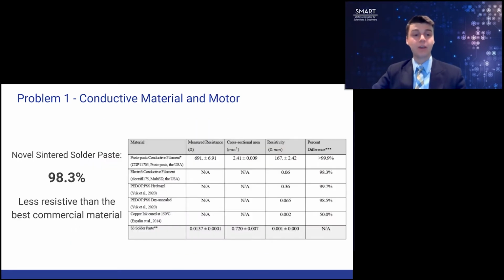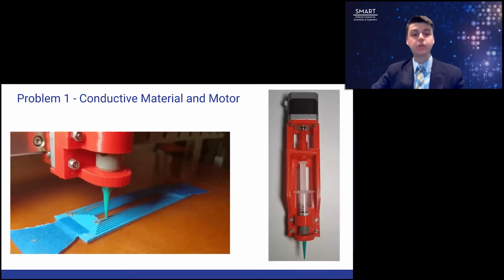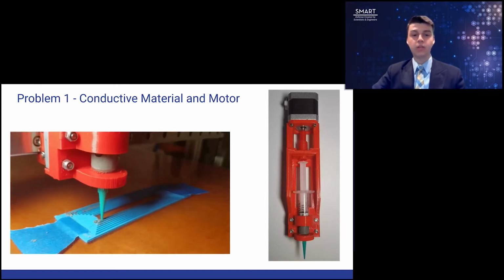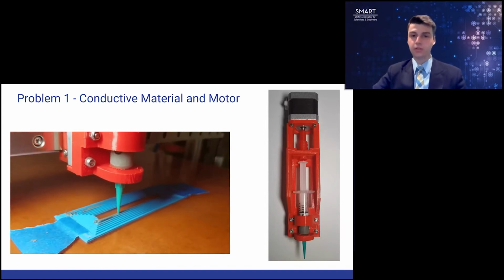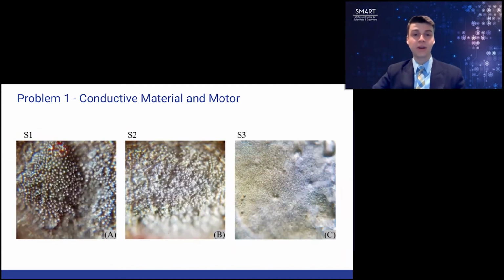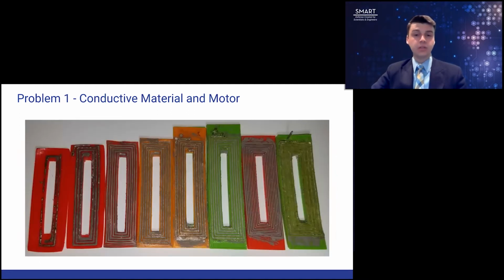My conductive material is 98.3% less resistive than the best commercial alternative material. The material is made by extruding a low melting point solder paste alloy through a 3D printed paste extruder onto a 3D printed substrate. The material is then sintered, whereby the individual solder particles are melted together to form a solid continuous trace. This process is actually quite difficult as the molten solder likes to bead up instead of lay in long continuous traces, which is not optimal for this application. So to make this process work as consistently as possible, I've created over 70 individual electromagnetic coil prototypes in order, again, to make that process as consistent as possible.